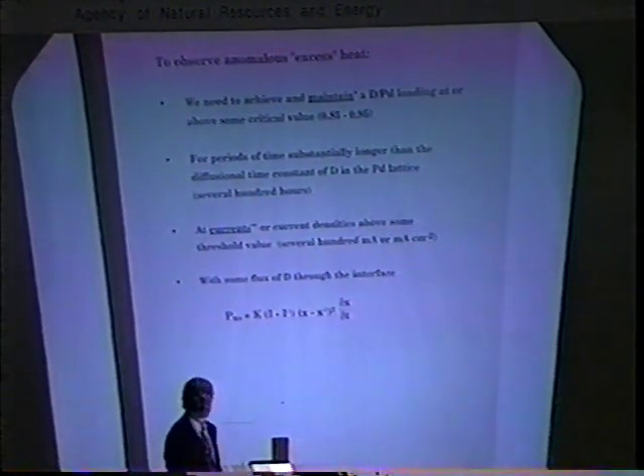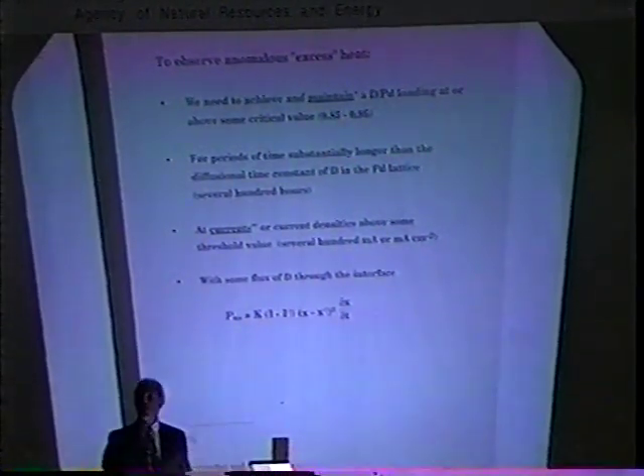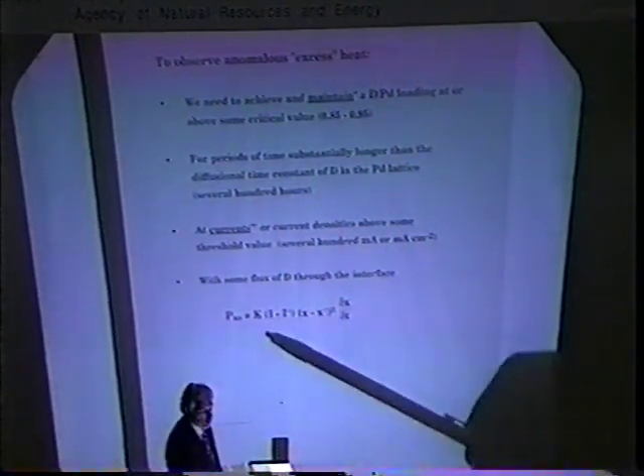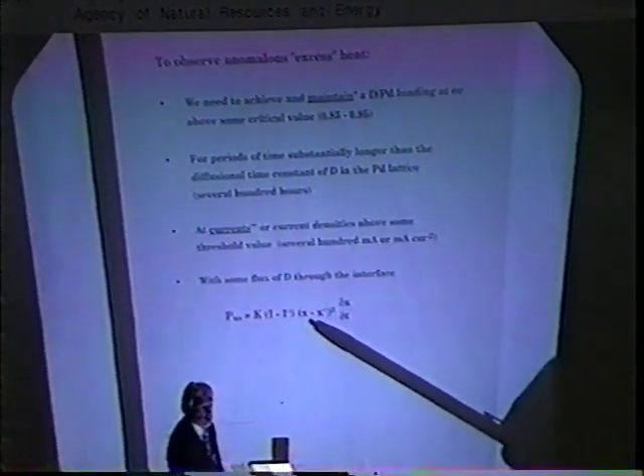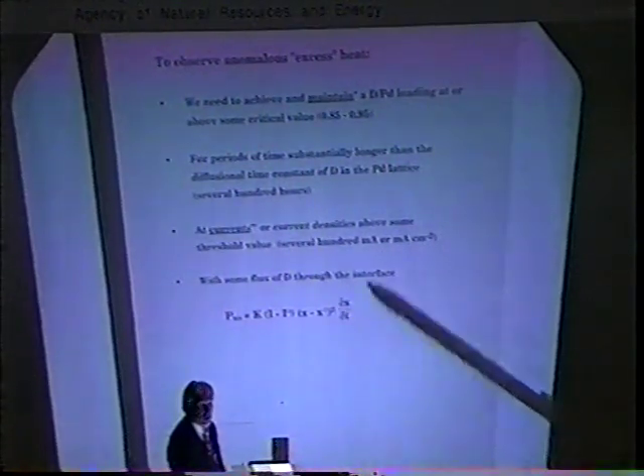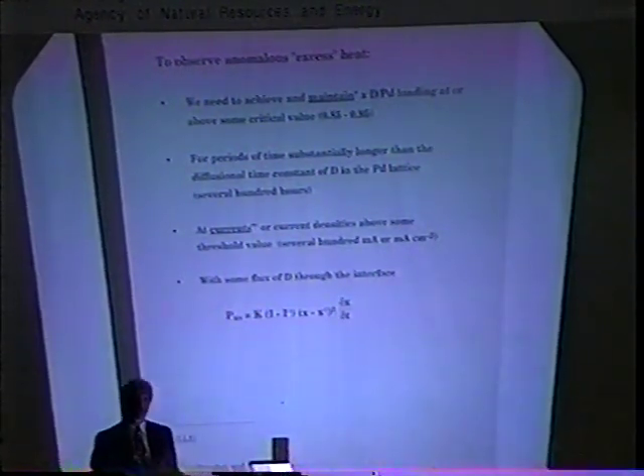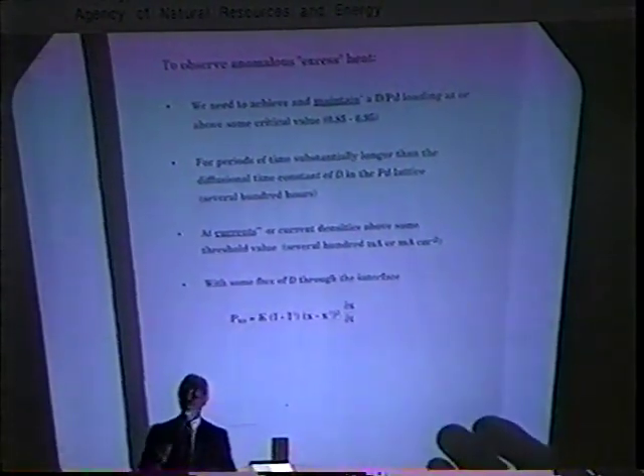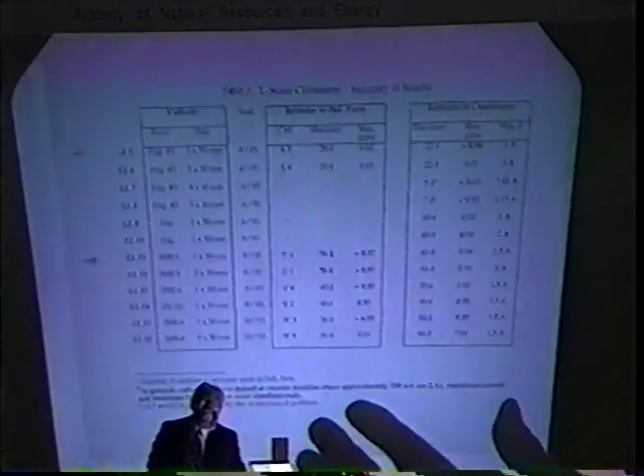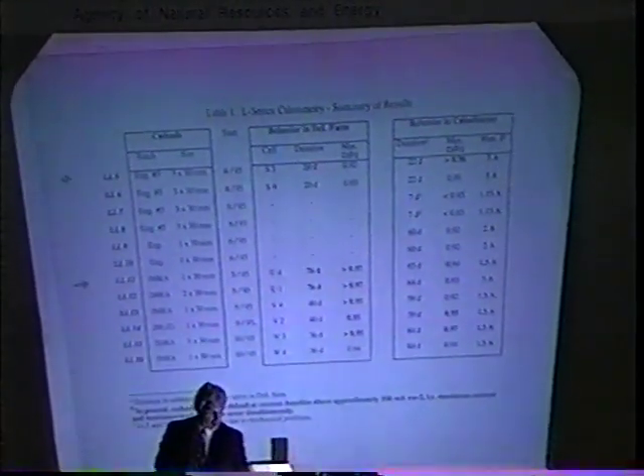And we've erected, and I presented at Monte Carlo, a little phenomenological model. Excess power is related to some constant, current above a threshold, loading above a threshold, possibly to the second power, and some flux criteria. There must be some variability of the loading, some flux of deuterium through the interface. We are simply trying to test that hypothesis. We're trying to do experiments to achieve those conditions so that we can see whether this hypothesis is sound or not. We've done many, many experiments since Monte Carlo.